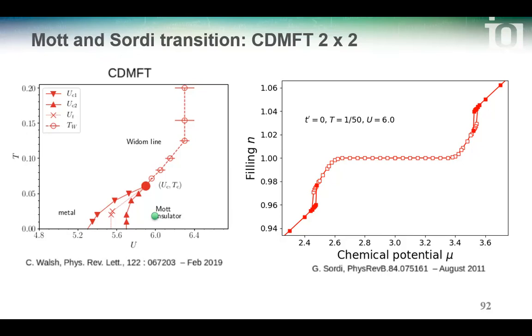But it's not going from 0 to some finite value, it just changes. Yeah, the same way as in a liquid-gas transition. It's the difference in density that is 0 at the critical point, and that increases as you go down along the first order line. You see what I mean? So you can take the difference in density as the order parameter if you want it to be really 0 at the critical point. And do you have a symmetry breaking? Usually phase transitions relate to some symmetry that is broken. Well, it's the same as in the liquid-gas transition.